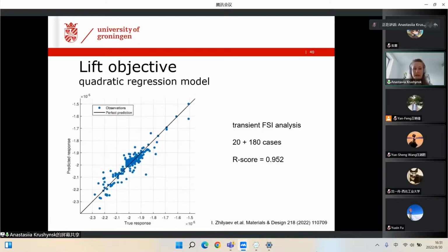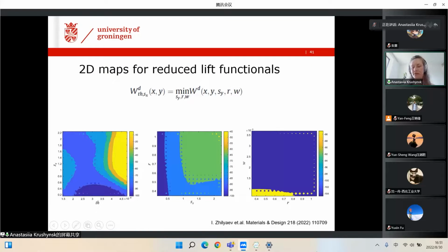And then we used a similar approach, and again a quadratic regression model, to analyze the lift objective. And here we wanted to maximize the lift of the wings. So for that, instead of eigenfrequency, we performed transient FSI analysis, for which we generated only 20 results, because it's very expensive to run such simulations. And then we calculated another 180 cases and fitted the model. Again, the R-score is appropriate. And we used that model to generate similar 2D maps, this time for reduced lift functionals, which give us insight about the importance of certain parameters as compared to the others, and also help us to find configurations and the corresponding parameter values that satisfy the requirement of the maximum lift. So more maps and more details can be found in this paper, you can see here.